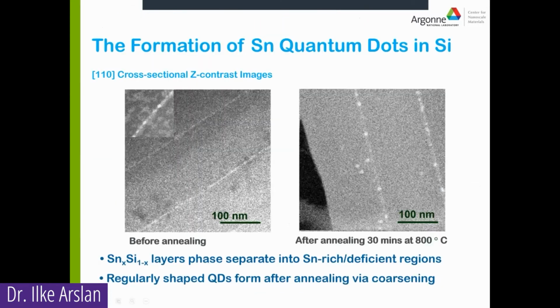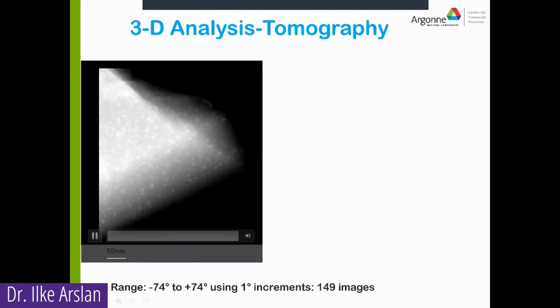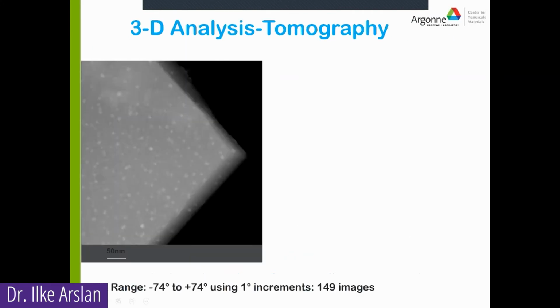But I will tell you one of the projects that we worked on, and this, again, back in 2004, was a much more novel technique. And we were able to look at these quantum dots that were forming within the silicon and not staying within the tin layers. And we were trying to investigate why this was. So this was before annealing, and this was after annealing. And you can see that the quantum dots have started forming, but they're not only inside the layers, but also outside of the layers. So we performed electron tomography, and I hope you can see that this movie playing now